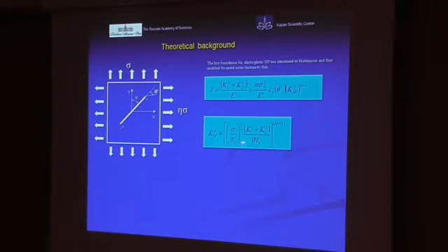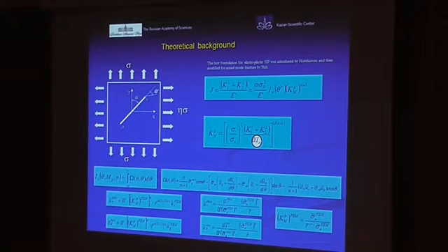The plastic stress intensity factor is a function of nominal stress, yield stress, Ramberg-Osgood parameters, elastic stress intensity factor, and the governing parameter of crack tip fields in the form of the J-integral. I would like to remind you that Professor Hutchinson introduced this governing parameter only for an infinite-size cracked body. We elaborated and extended the HRR solution and proposed a numerical method on the basis of the finite element method to determine this governing parameter for specimens and real structures.